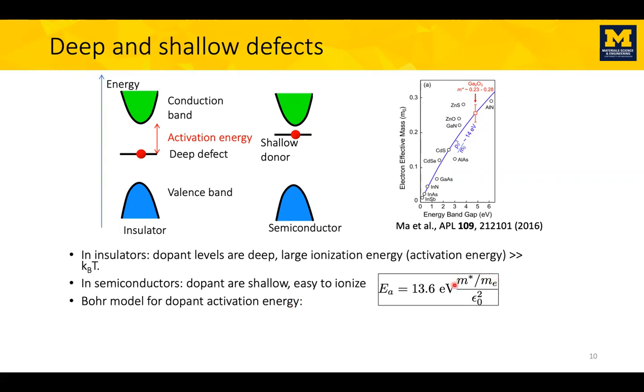The mass of the electron needs to be modified to that of the effective mass coming from the band. Band electrons move with a different mass than free electrons. And also take into account that the material screens the Coulomb interaction through its dielectric constant, which comes in as the square because of the Bohr model. So in semiconductors, the effective mass is typically a fraction of the free mass, say 0.1 electron masses.